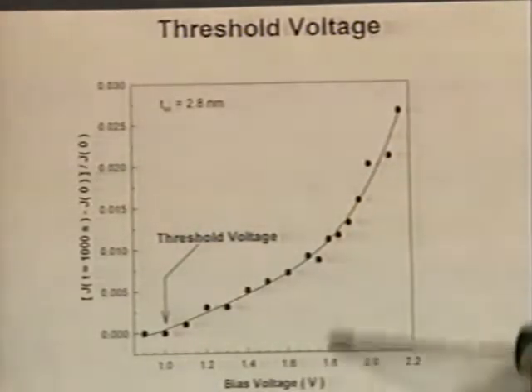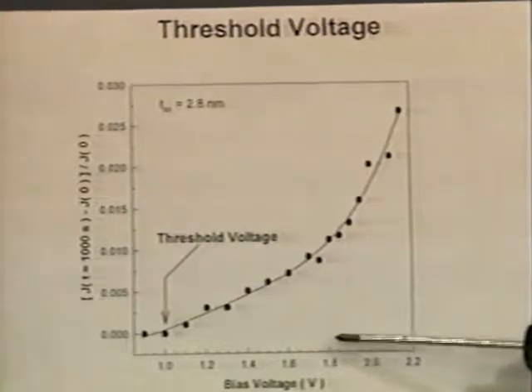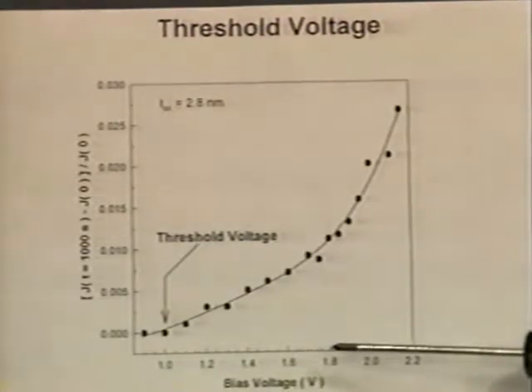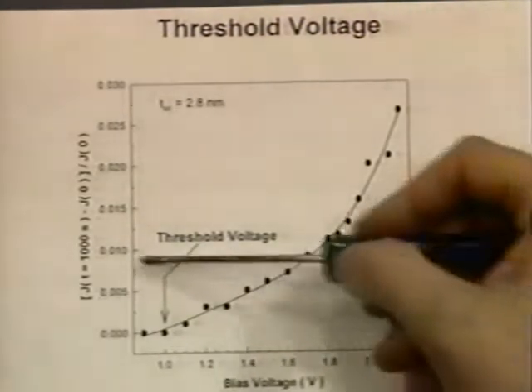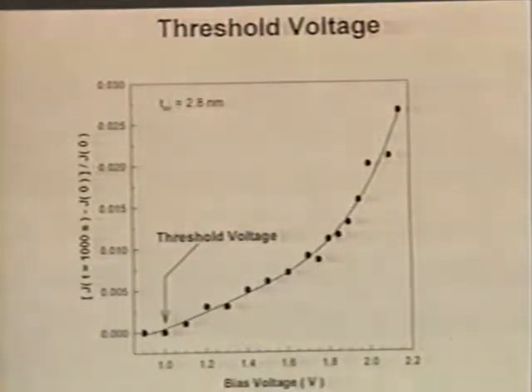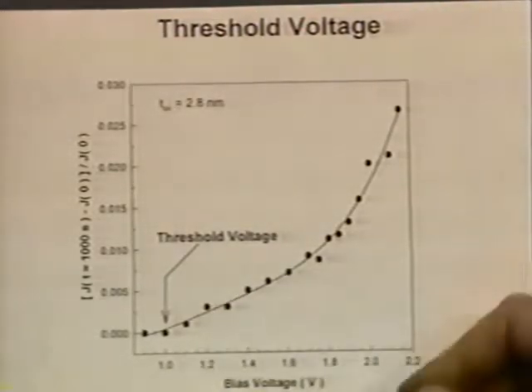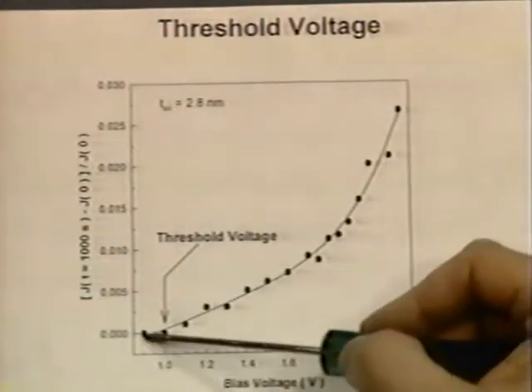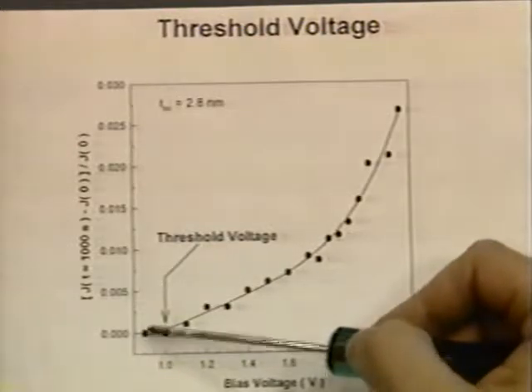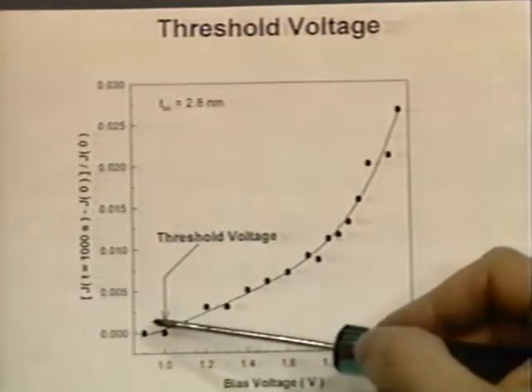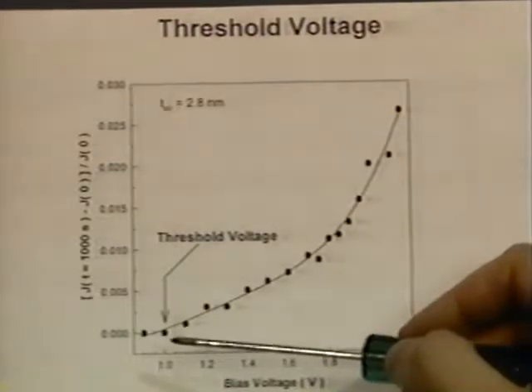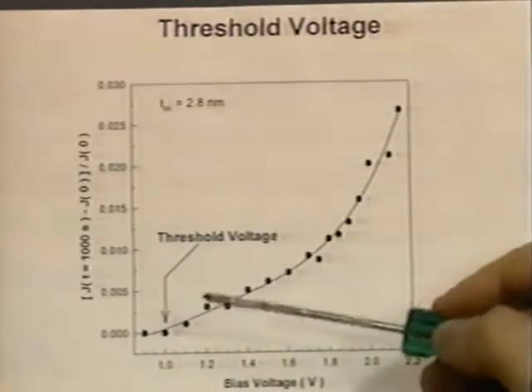But if you sit at a lower voltage, you have lower. You know, the voltage just changes the rate of defect creation. You have maybe 1% change in the current after 1,000 seconds. Sit at 1.2, it's even lower. At 1 volt and at 0.8, for example, we can't measure, even after sitting for several weeks, not just 1,000 seconds, we can't measure defect creation anymore.